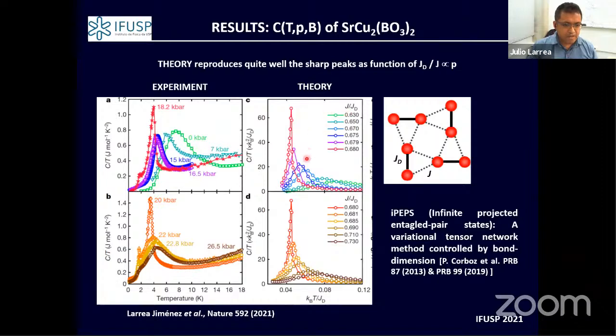And after, of course, passing through simply an enhancement of this ratio of the dimer exchange coupling, you again reproduce the decreasing of the sharp peak, like the experiment also shows.